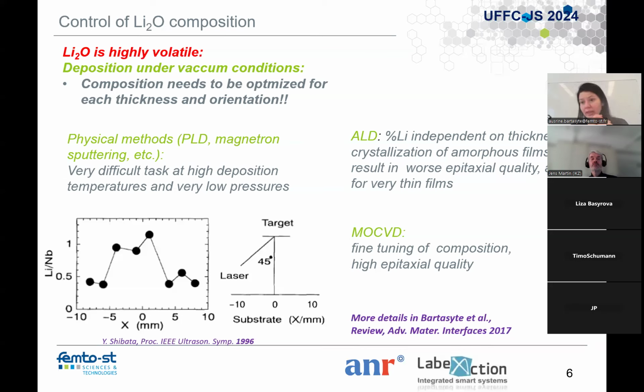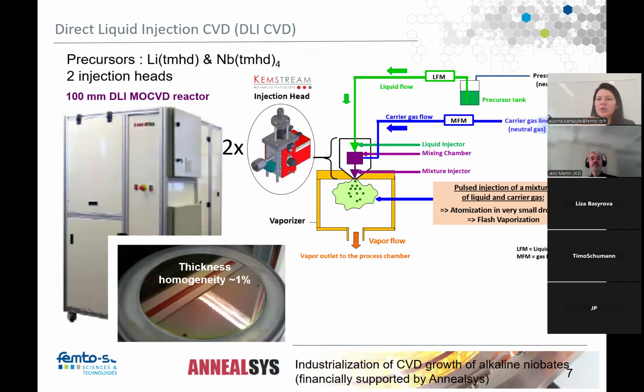I had the opportunity to also do sputtering of lithium niobate, but I finally preferred to work on CVD techniques, which allow you to tune the composition easily from one deposition to another, and to adjust very finely. So at FEMTO-ST, we worked in collaboration with Annealsys, who gave us a DLI-CVD machine for 4-inch wafers. We have two injection heads, and we use solutions of metal organic precursors: lithium THD and niobium THD4.